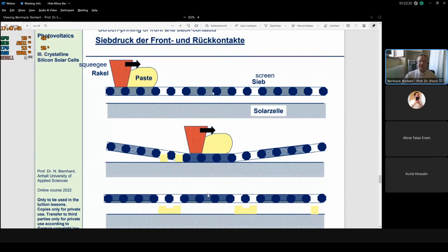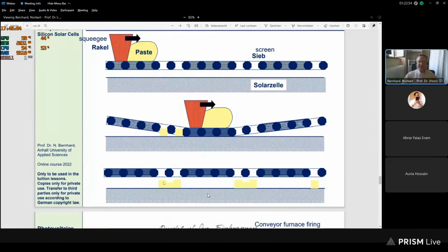We have a paste, which is moved by a squeegee across this wafer. The squeegee also presses it down and presses this paste through the open regions of the screen, and then something like this remains. And since the paste, of course, has a certain viscosity, after some time you wouldn't see the structure any longer. You just get something which has flown apart. That means a shape, as I described at the moment with my cursor.